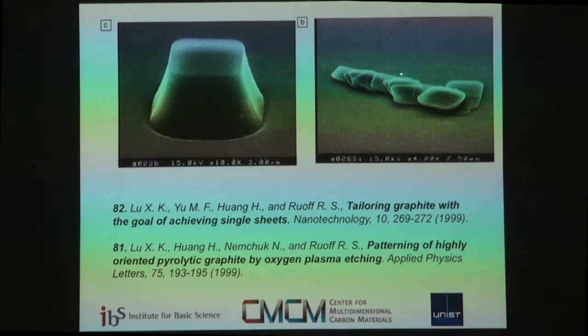But there are fascinating issues associated with friction. If you have the A-B stacking between layers, then what you have is a relatively deep potential energy well in terms of how the layers are locking with each other. But if you misorient it off that A-B stacking, then it smooths out the potential energy surface dramatically. And you can have what may be superlubricity, or almost frictionless sliding of one sheet with respect to another.